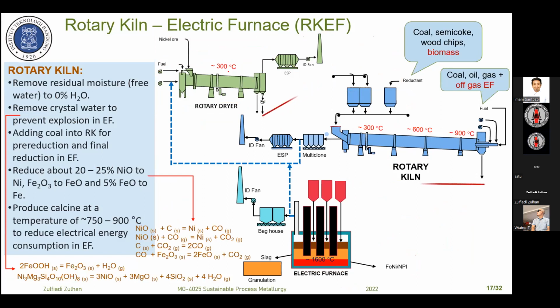The next is the rotary kiln. The task of the rotary kiln, the first is to remove residual moisture from the ore. At the input we get 20%, and this should be removed to 0%. The removal of moisture takes place around the first third of the kiln, in this area. And then remove crystal water to prevent explosion in the electric furnace. Usually the crystal water should be less than 1%.